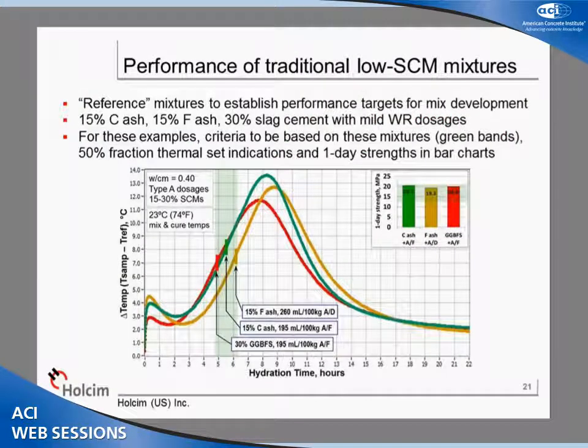Now here's how we would go about using this technique or this approach to actually model successful mixtures and reproduce their performance in highly sustainable mixtures. These are 3 different mix designs from common concrete in the marketplace that have been modeled in paste in the laboratory. And they are the same 3 materials that we've just investigated: a slag cement at about 30% replacement, an F-ash at 15%, and a C-ash at 15%.